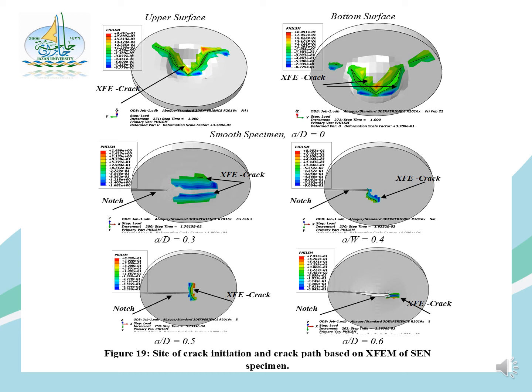However, for a/D in the range from 0.4 to 0.6, the crack emitted from the notch root, but there are other cracks emitted from the smooth surface near the notch in this figure. This is in agreement with other results for the J integral and the crack opening displacement. Also, it is worth noting that the final failure is not affected by the presence of the SEN. The shape of the final failure is a circular shape.